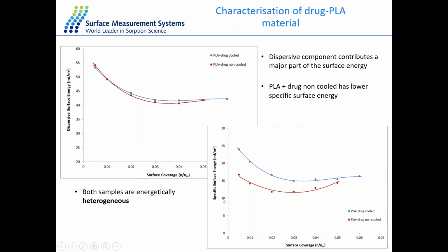This plot looks at the specific surface energy across increasing surface coverage. In this case, what we can see first of all is that it's a lot lower than our dispersive surface energy. So our dispersive surface energy contributes to a much more major part of the surface energy. What we can see is that the cooled material has a slightly higher specific surface energy than our non-cooled material.